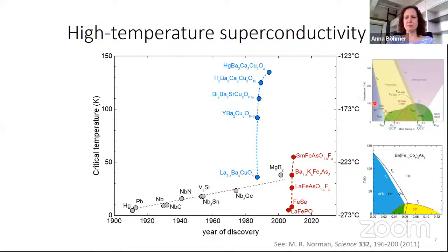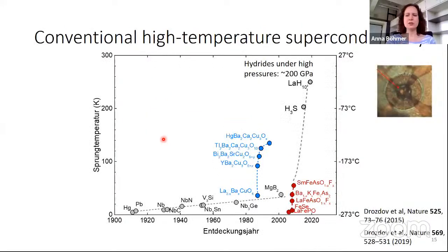So this is a phase diagram, a temperature and a tuning parameter to the right. And what you see is a superconducting range. That's the green part here. It's the green-yellow part here. What they have in common, there's something else around here or here. So if we think about the introduction, that looks similar. So our new paradigm is, well, we want to look for magnetic phases or other phases that are suppressed. And around the point where they're suppressed, maybe that's where we find our interesting superconductor. That is a fruitful way. But it's not the only way.